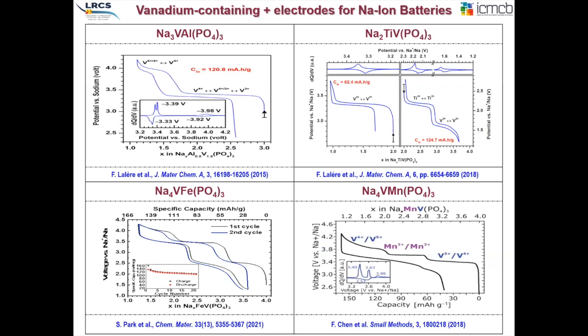We played quite a bit with many of these compounds, and depending on the transition metal element you put, with aluminium versus vanadium, we can have many different properties, many different operating redox voltages. We can substitute vanadium by aluminium here. We can substitute vanadium with titanium, with iron, as I will show a little bit later, and with manganese. In these two cases, because we can substitute with iron 2+ and manganese 2+, we can end up with a cathode containing four sodium ions, which is very important if we want to increase the energy density and the capacity of these NASICON electrodes.